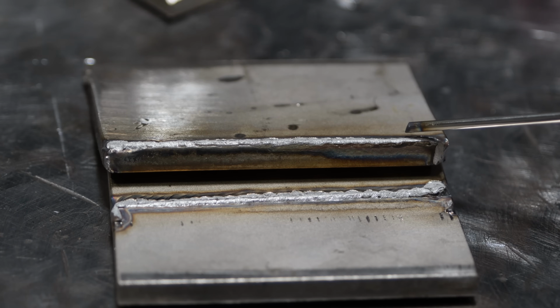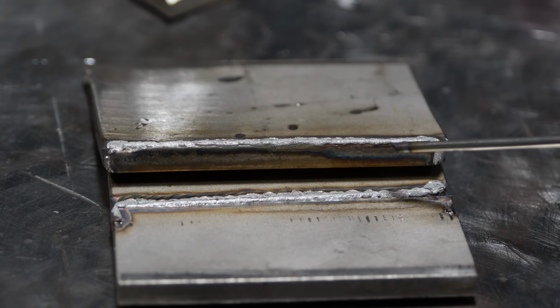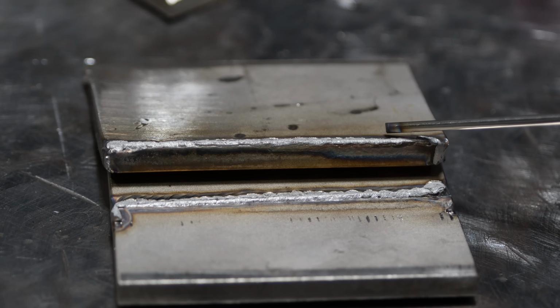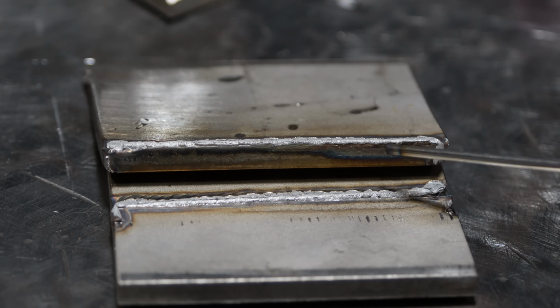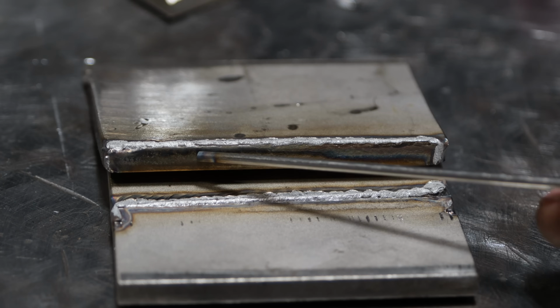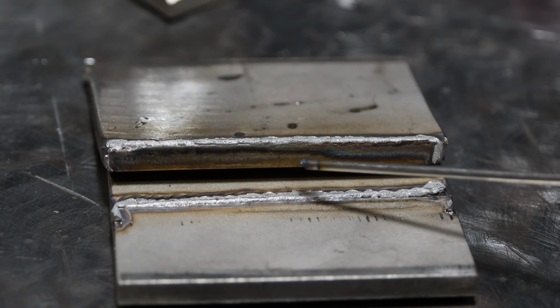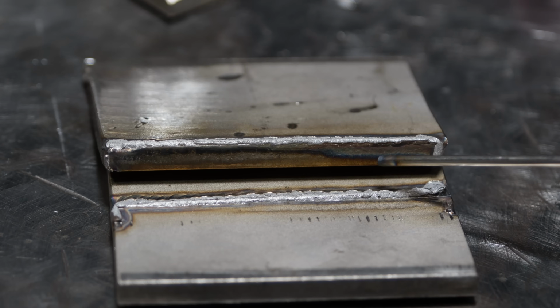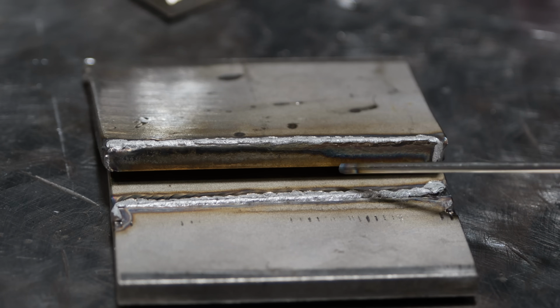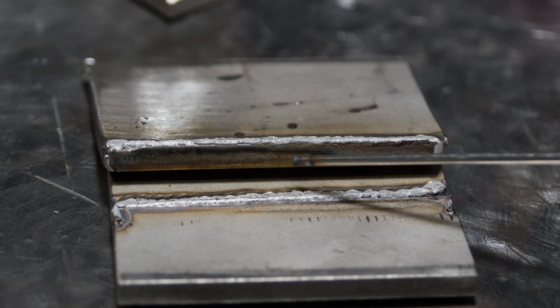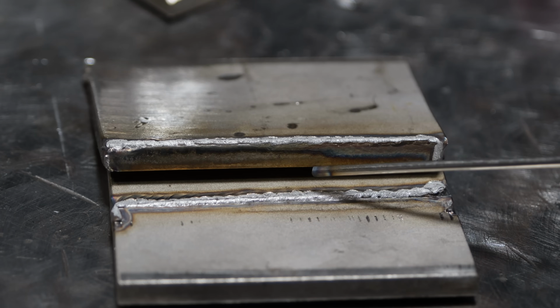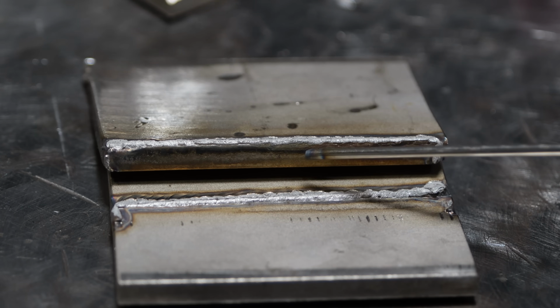So I broke the plate in half and I forgot how strong TIG welding is on stainless. This actually took a lot of force despite the weld being undersized for the material. But looking at this, I don't really see any evidence of sugaring underneath this plate, anything that would make me question that there'd be a strength related issue. Now there is not much, if any, penetration on this, and I wouldn't expect it. When you weld stainless steel properly, aka like in this case 140 amps, and you're moving fairly quickly, you simply don't have the dwell time to get a lot of penetration, and that's perfectly fine.